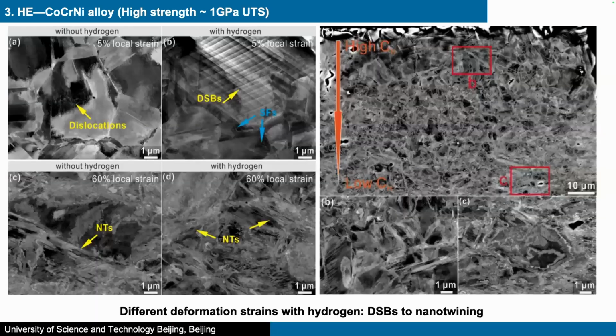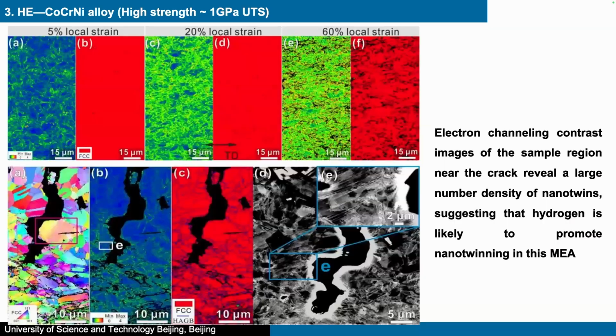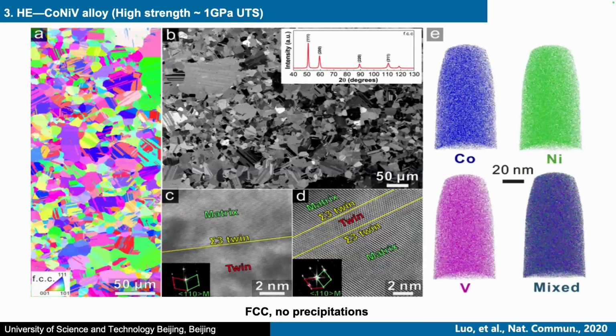We found some deformation shear bands can transform to nanotwins with different local strains, and found the nanotwins change. This is the EBSD results to observe the cracking initiation and progress. And we found the formation of nanotwins can enhance the hydrogen embrittlement resistance, and also hinder the cracking propagation. And we choose another type of alloys to see these results.